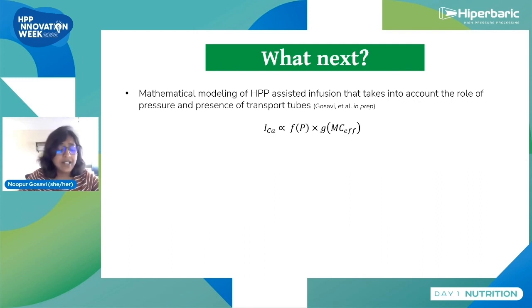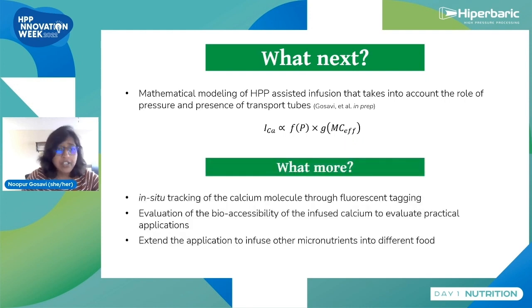What we need to do is understand how the application of pressure changes with the presence of transport tubes. So what my research now does, and you'll see this publication out soon, where we look at mathematically modeling the amount of calcium that can be infused with increasing pressure and change in microstructure. What else can the scientific community do? We need to look at how the calcium molecule actually travels throughout the matrix as the high pressure is processing. And we need to evaluate how the bioaccessibility of the infused calcium translates, because higher infusion doesn't mean higher bioaccessibility. And we need to extend this application into different food materials with different micronutrients.